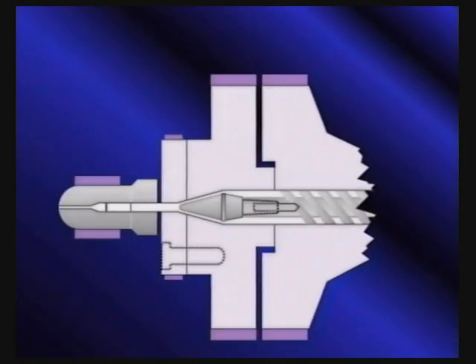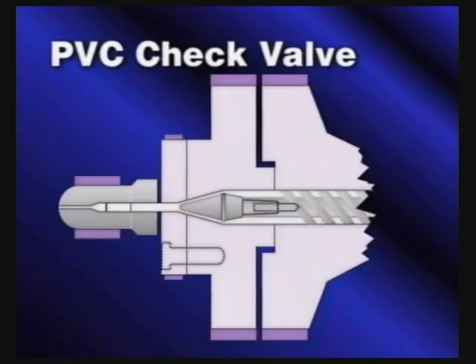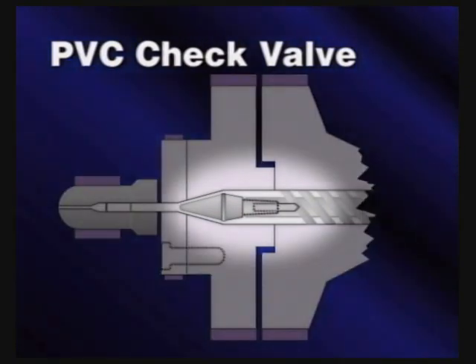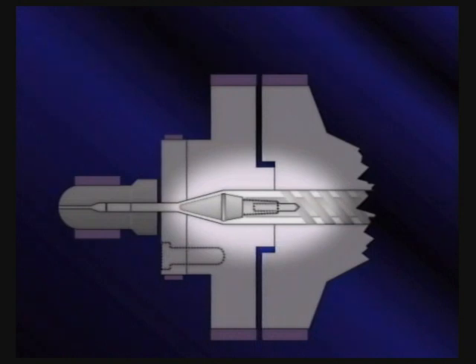A check valve specifically designed for PVC does not block the backflow of material as well as the slip ring check valve. However, PVC does not tend to flow back during injection due to its high viscosity.